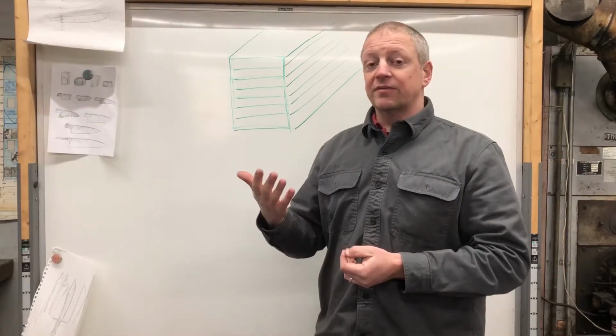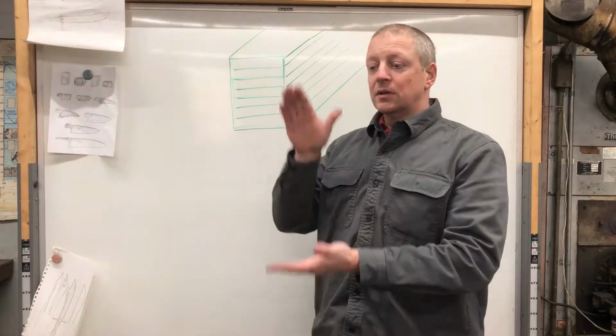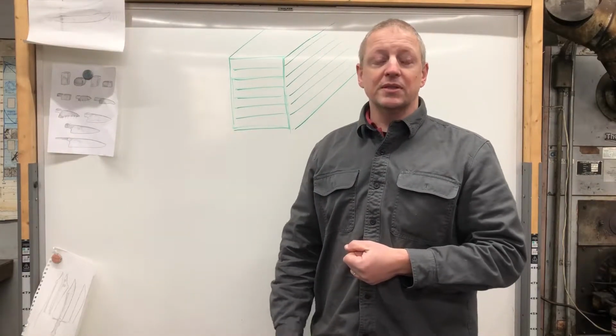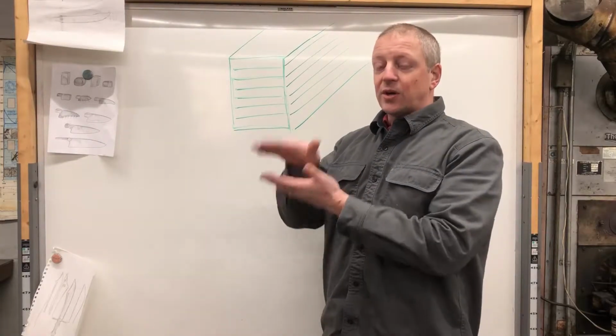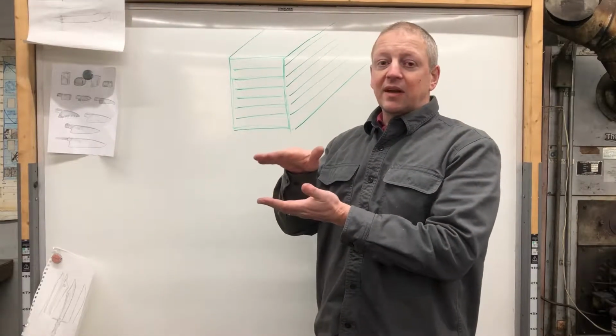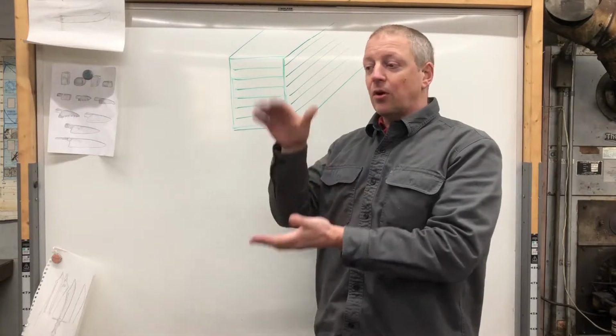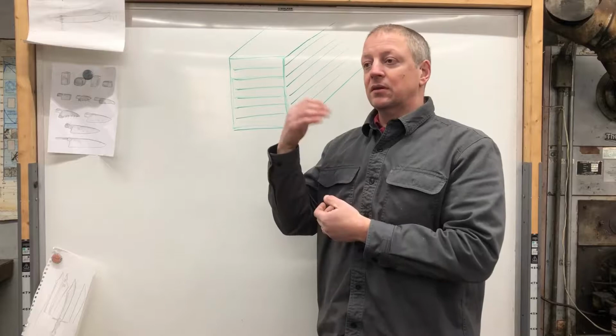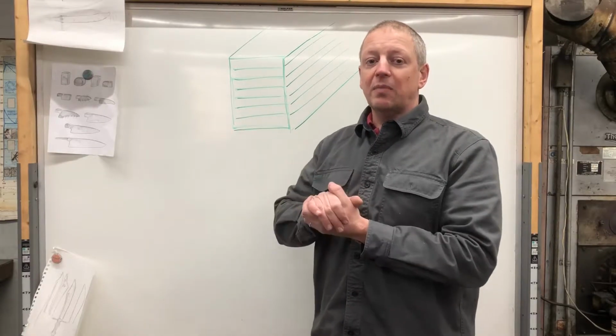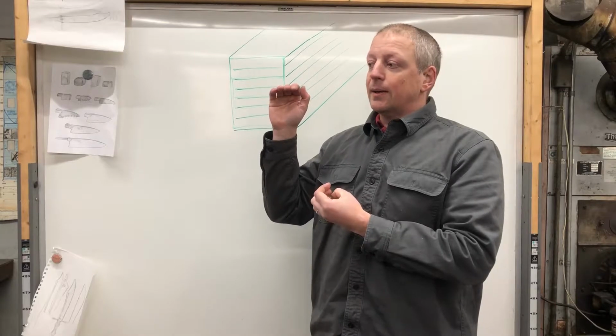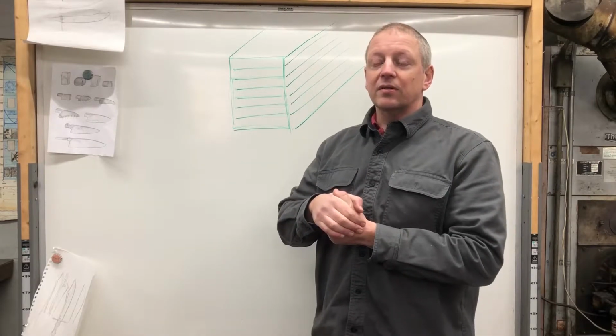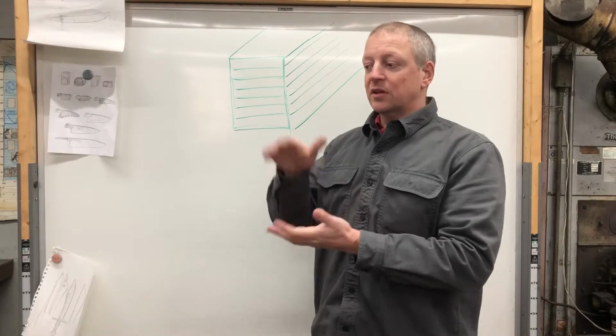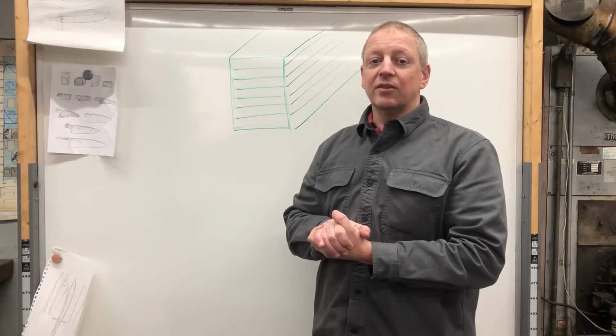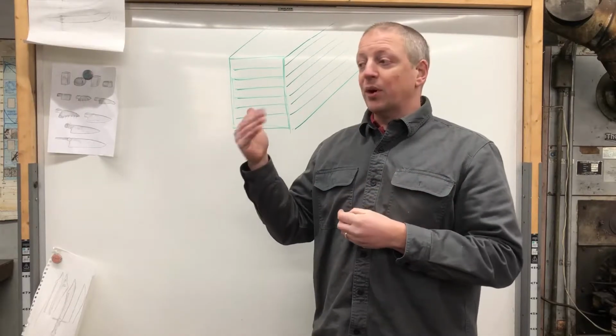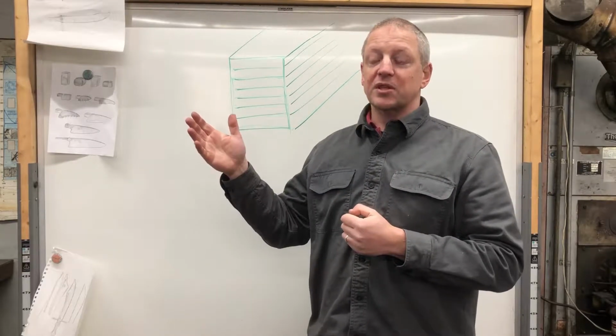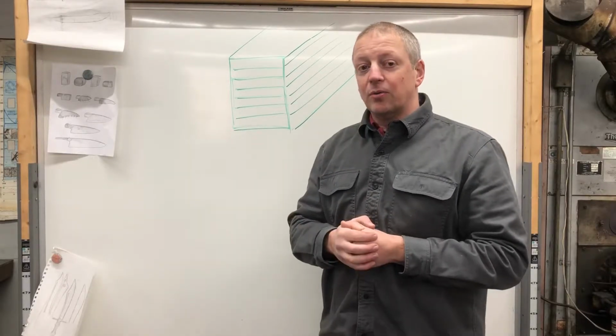Once you've done that 5 to 10 minute soak, bam, you put it together. It's a solid piece. What I like to do is, I do that initial squeeze to make everything tight, do the 5 to 10 minute soak, set my welds, just do one round to set the welds, toss it back in there while it's still nice and hot, and give it another 3 to 5 minute soak, and then really set everything final. And at that point, you should be able to just go hog wild with this material. It's going to be incredibly strong welds.